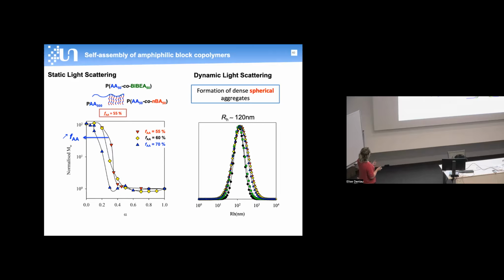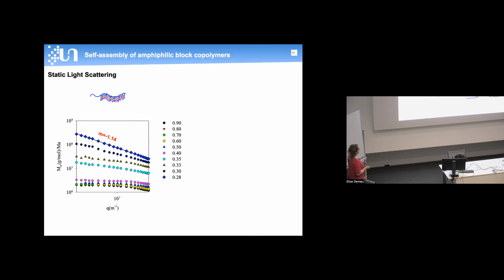Unfortunately, if we compare the ratio between the molecular weight and the hydrodynamic radius obtained by dynamic light scattering, we could see the formation of dense spherical aggregates. And finally, we found that by using a bottle brush with a shorter length of the first hydrophilic block and a longer backbone of the brush, but with a shorter length of the brush, the aggregation behavior